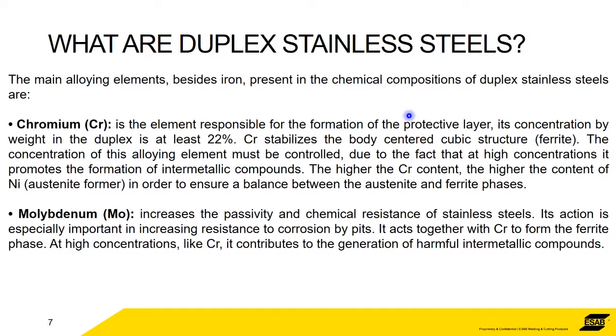Nickel wants to create austenite. Molybdenum is to increase the passivity and chemical resistance. That's why molybdenum is used. It's very good at increasing the resistance to corrosion, from pitting corrosion. High concentrations of molybdenum want to create harmful intermetallic compounds, and I'll illustrate that a bit more later on.